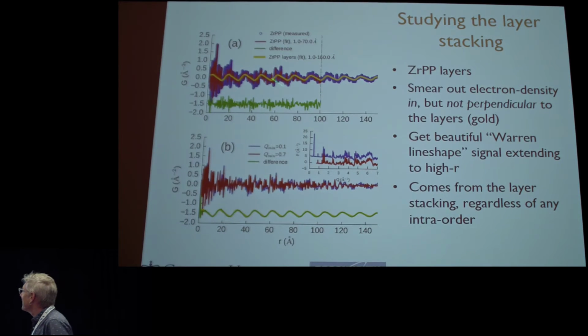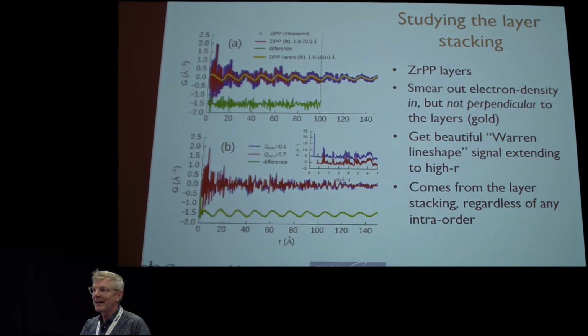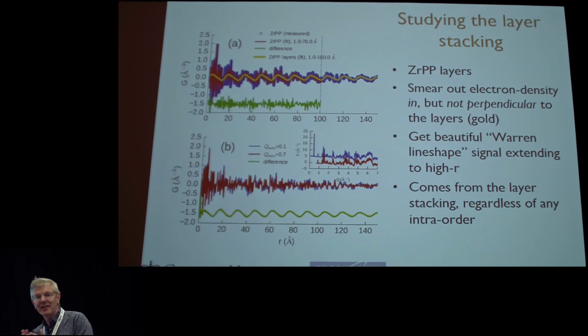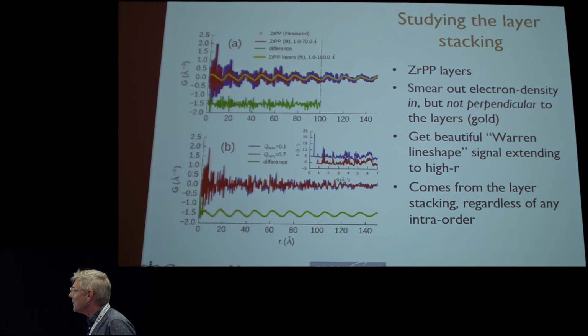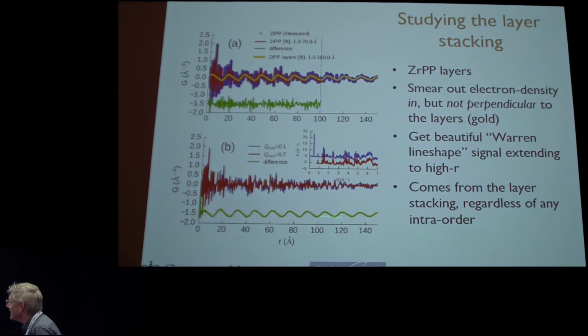This is actually a famous Warren line shape, which is the kind of line shape you get when you have a 2D object and you study it with powder diffraction. So Warren makes his appearance again. And what it is, it's actually showing the electron density distribution, the one-dimensional electron density modulation coming from these stacked layers. So it's telling us that even though we have a fair amount of structural disorder in the system, we have very well-ordered layers that continue up and up and up. And then we can fit models which don't have the layers in, and then we can actually see that the layer information is there. So we're getting information about the morphology.